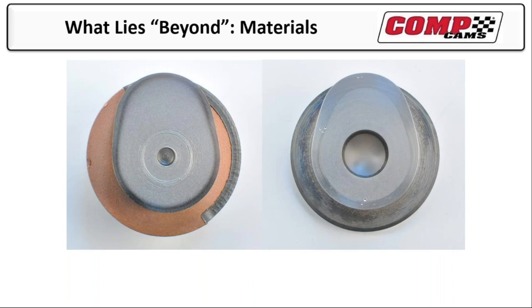If you look at the cross section of the cam on the right, this one's 5160. You can see where I've done hardness checks, and you can see how the hardness changes. It's a quarter-inch deep on the nose and still over 100 thousandths deep on the base circle. This gives us a lot of flexibility on what grinds we can put on it. It also is just a lot deeper road.